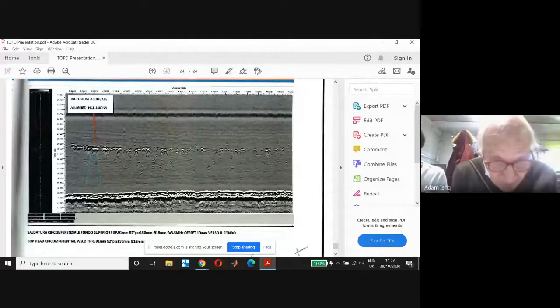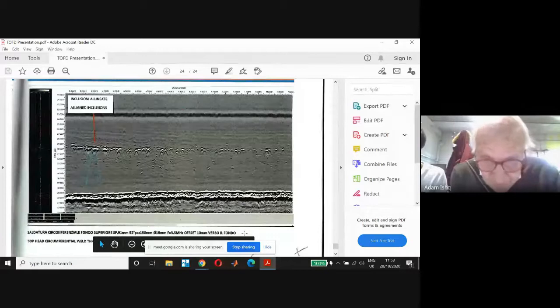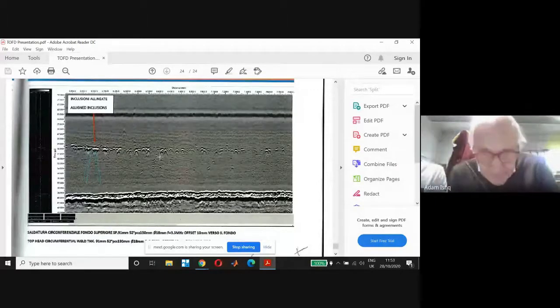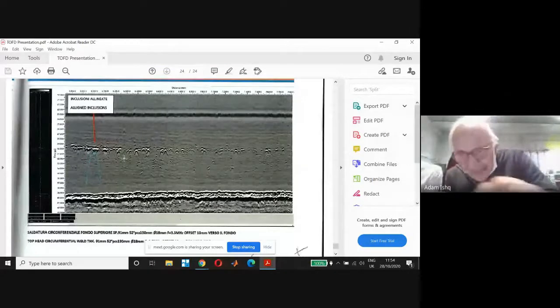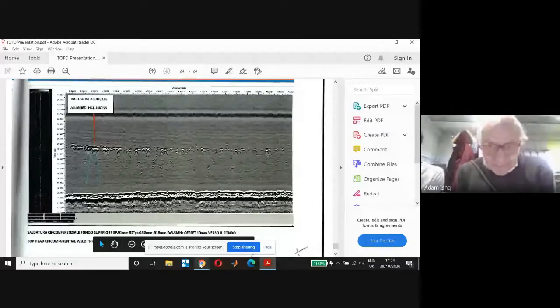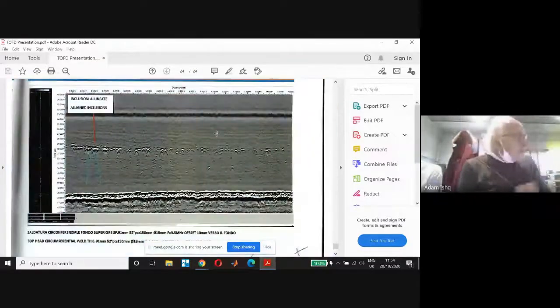Yes, you are right. That means this is a circumferential weld, and you have inclusions because when you see all these arcs, that means there is a distance between the different inclusions. So this is a typical aligned inclusion, very clear, and it's fantastic to see. Also very important, as you see, the image shall not be flat. You have to see some small waves, not in zebra color, but in shadow. That means this is in practice the noise of the ultrasound that goes across the material. This is the typical area where we go.